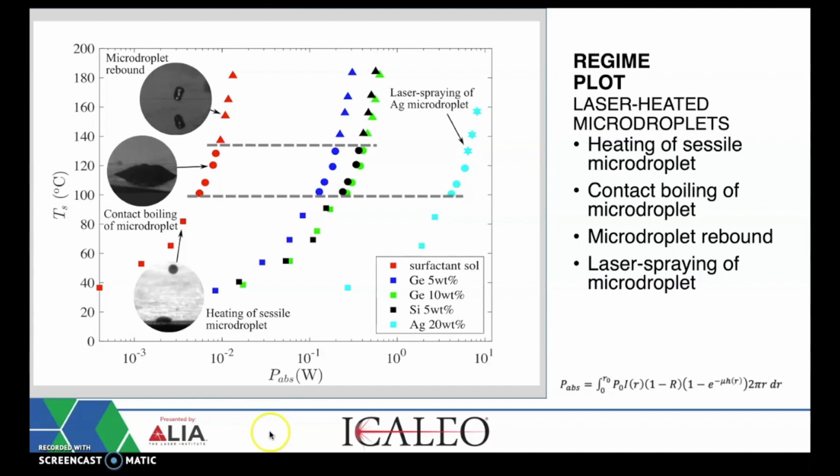It reaches a certain height until the kinetic and potential energy are balanced, and then it falls down again onto the substrate. And this happens many times. It is not restricted to just one time. Another observation is that the characteristic vapor layer in the Leidenfrost phenomenon insulates a droplet from the hot solid surface. Thus, the droplet doesn't experience nucleate boiling and bounces back because the vapor overpressure beneath the bottom surface overcomes the droplet's dynamic pressure.